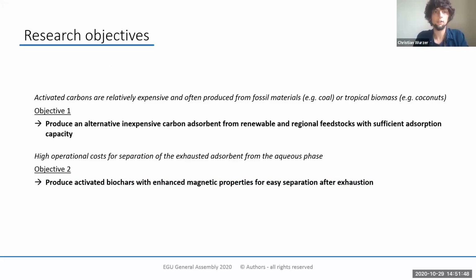So the first one is that the biochar should be inexpensive, produced from renewable and regional feedstocks, and have a sufficient adsorption capacity. So I'm not assuming to be able to directly compete with the capacity of a fossil-based activated carbon, but at least it should be comparable. And the second objective, to decrease the operational costs of actually applying the adsorbent, is to produce activated biochars with enhanced magnetic properties to be able to separate the adsorbent easily from the water phase after use.